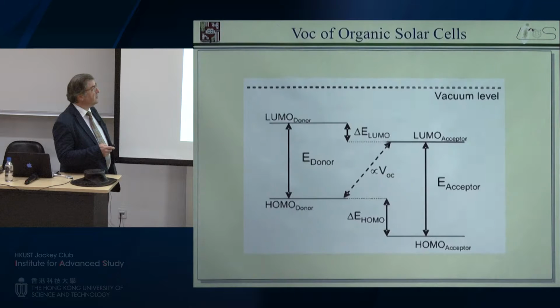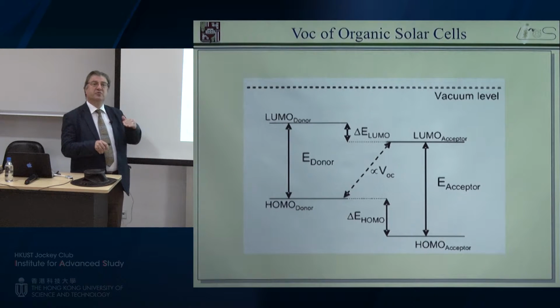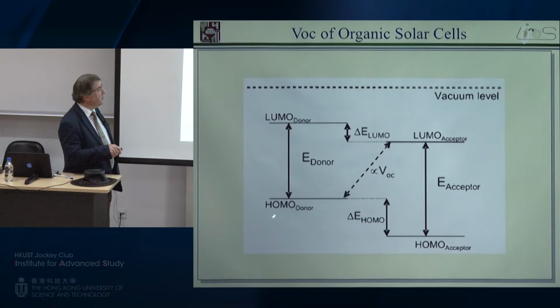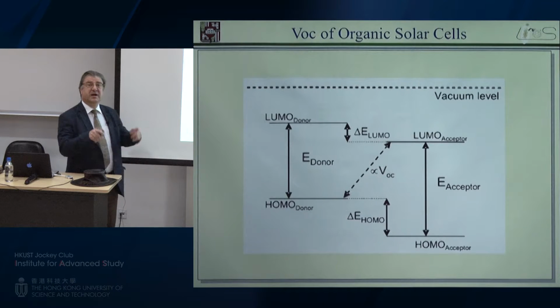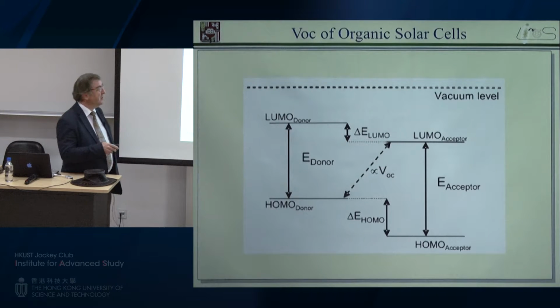And the open circuit voltage is up to now generally accepted to be between the quasi-Fermi level of the donor, which is more or less close to the HOMO level, the highest occupied molecular orbital, and the LUMO, the lowest unoccupied molecular orbital of the acceptor. So that distance is more or less limiting the quasi-Fermi level splitting.